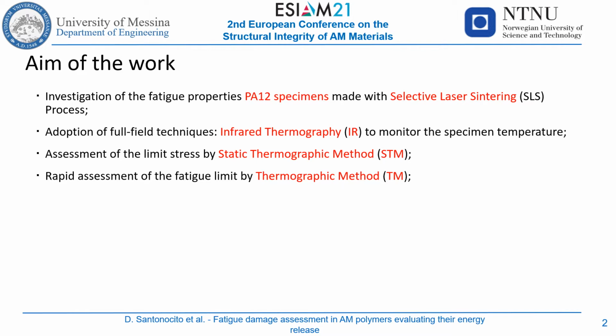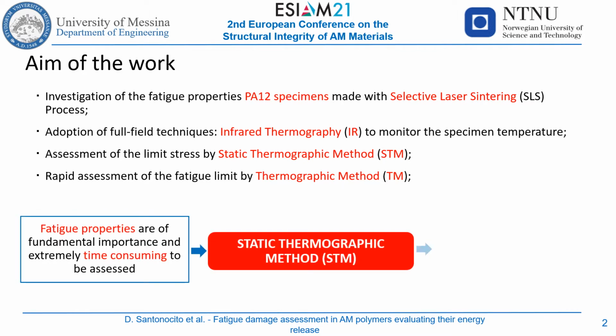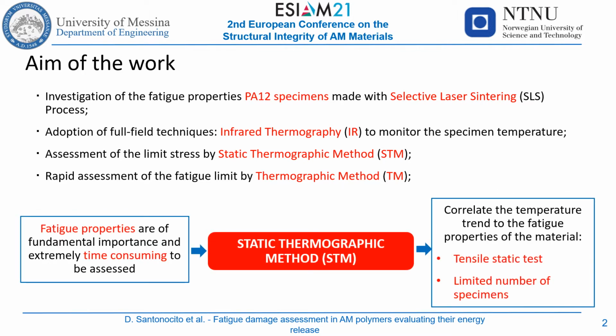The mechanical properties of the material were evaluated, and the temperature trend of the specimen's surface was monitored during static tensile and fatigue tests, applying the static thermographic method and the thermographic method. In particular, the static thermographic method is proposed as a rapid test procedure able to correlate the temperature trend to the fatigue properties of the material during static tensile tests, adopting a very limited number of specimens.